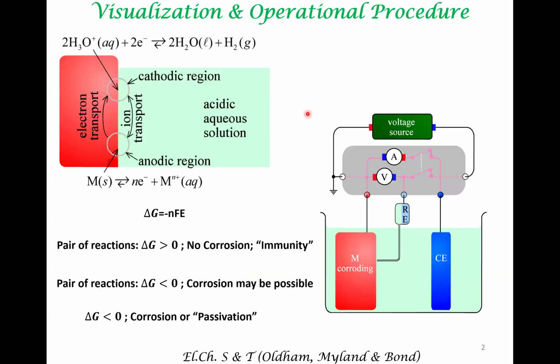So the central challenge in the case of uniform corrosion is that the anodic region and the cathodic regions of a corrosion cell are not separated via an electrolyte. So we discussed how these anodic corrosion reaction and the cathodic reaction can be visualized and operationally implemented via a cell like this, wherein this sample, which is getting corroded, is distinctly separated from a counter electrode. This not only helps us in measuring voltages and currents.